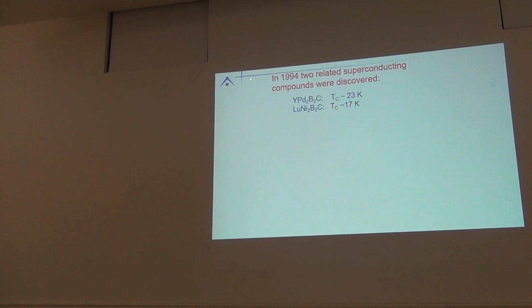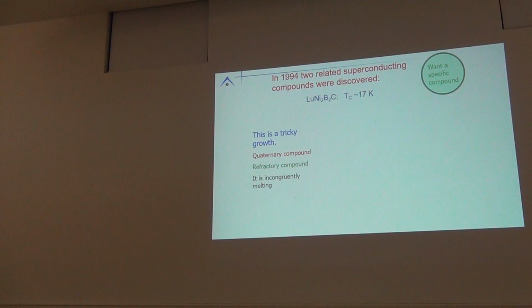Okay, so 1994, there were 2 related superconducting compounds discovered. You had yttrium palladium 2 boron 2 carbon, and lutetium nickel 2 boron 2 carbon, quaternary compounds, and they had actually very good TCs. The yttrium palladium had a TC rivaling the highest non-high TC compound of the time. Okay, so we really wanted to try to grow these. Now, how do we do that?